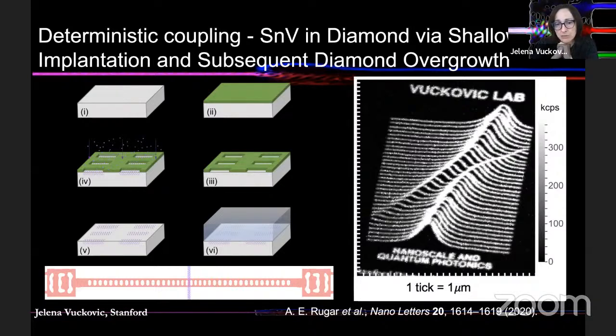And for addressing spatial inhomogeneities, we've developed, in collaboration with the groups of Zhixun Shen and Jelena Vuckovic at Stanford, the technique of shallow ion implantation and subsequent overgrowth. Really, the idea here is to introduce color centers at desired positions inside of the structure with minimal damage. And normally people introduce color centers by high energy implantation, which of course always introduces damage and moves some carbon atoms around and changes the local environment for color centers. What we instead did in this work was shallow ion implantation at much lower energies.